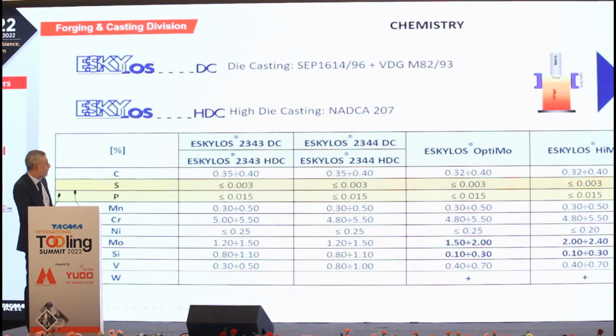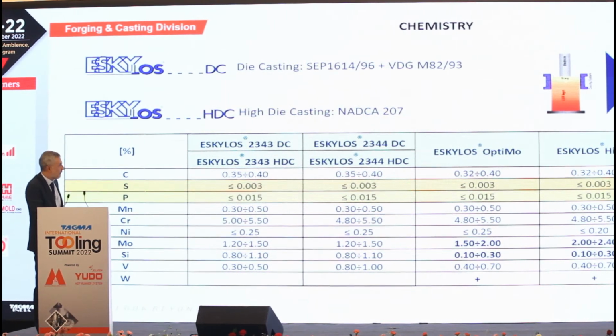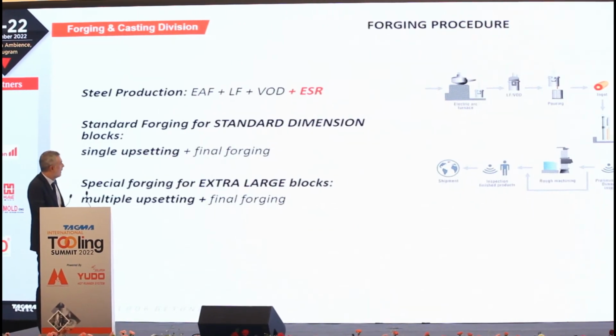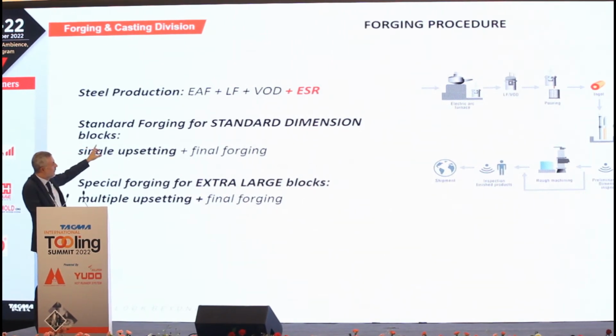die casting. We have been working also on the chemical analysis, focusing on the level of sulfur and phosphorus content in order to keep them very low, because they can have a negative influence on the performance of the steel. And then moving from the standard steel grades 2343 to 2344 to our new proposal for light alloys die casting, Eskylos OptiMo and Eskylos HiMo. So steel production, again, electrical furnace, ladle furnace, vacuum oxygen degassing, plus electroslag remelting.